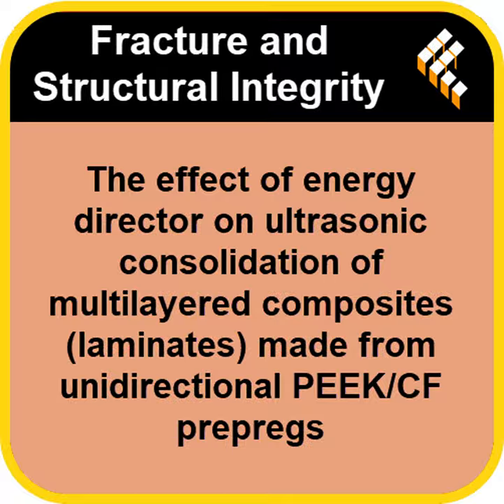And the numbers really back that up. They do. At that rational duration, 800 milliseconds, the ILSS they got without the ED was over 50 MPa. That exceeded the absolute best number they got with the ED, that 40 MPa, by a solid 25%. So you add the helper and you weaken the final product by a quarter. A very powerful lesson in unintended consequences. It is. But we have to put this in context.